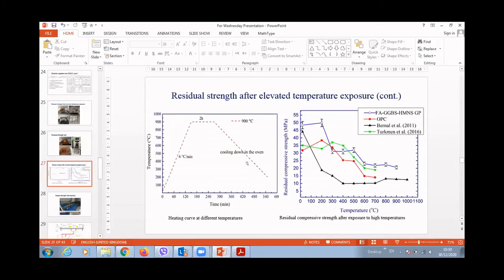We heat the oven to 900 degrees, then put the samples inside for 2 hours. Then we cool down just by opening the oven door and leaving them in the room, and then go for the compressive strength test.